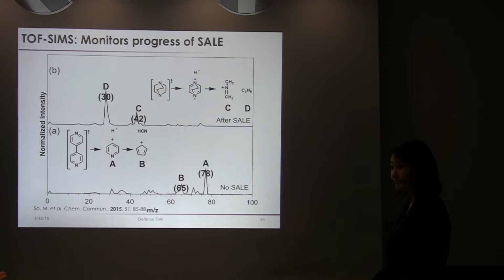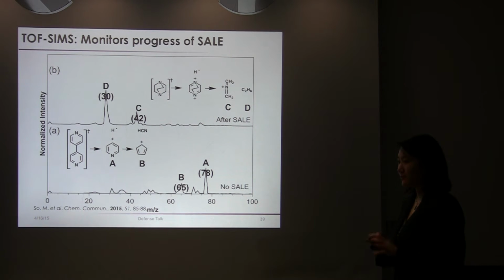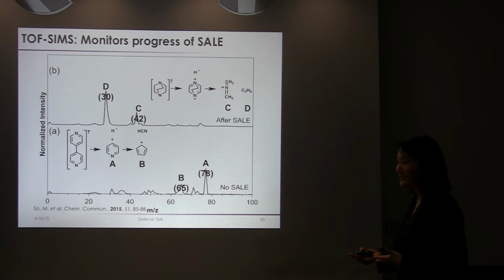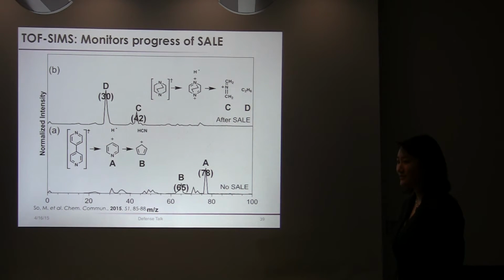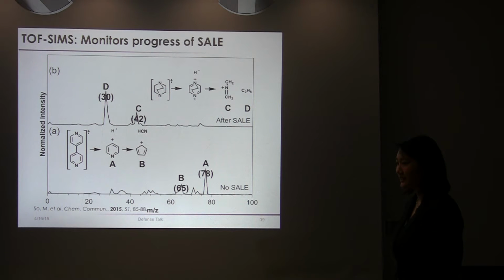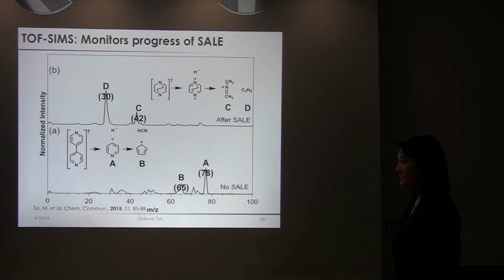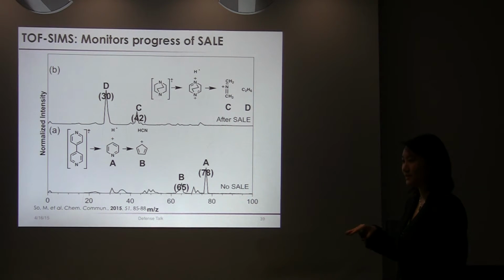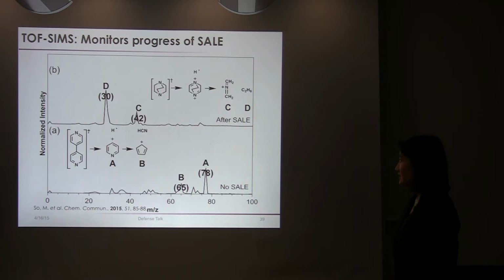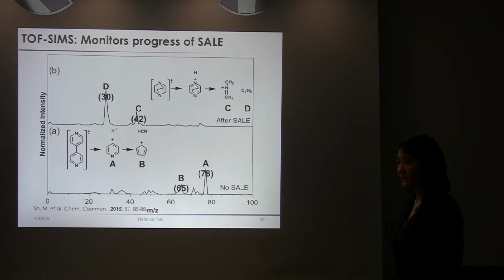And how long does it take to etch through a film? There's a lot of vacuum in these. Yeah, pretty quick to etch through. I think it depends on the film composition, whether it's organic or inorganic. But in this case, it takes close to a minute and a half to etch through the entire film because it's very, very thin. So if you had compositional modulation, could you get anything useful out of depth profiling? Yes, you could. You can monitor whether there is appearance of different species in the film as a function of depth. And you could also do this with XPS depth profiling as well.